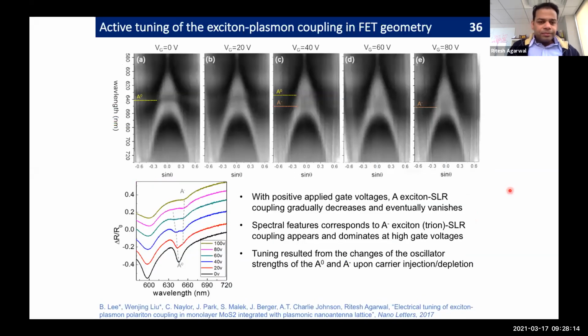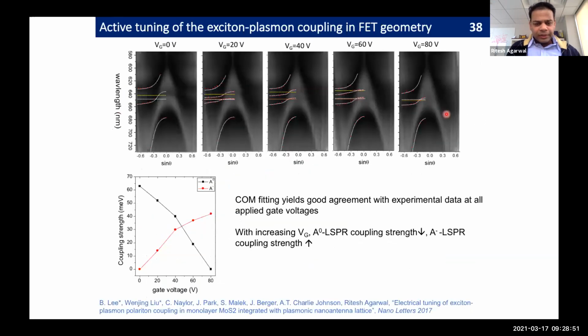So indeed, at 0 gate voltage, we saw this level repulsion at the A exciton region, and then as we injected carriers, we started to see a weakening of this A exciton level repulsion, and some perturbation in the line shapes at the trion, because we're injecting carriers, so it starts to form trions in the system. And as we inject more and more carriers at larger gate voltages, the A exciton level repulsion simply disappeared, and we started to see more perturbations in the line shape at the trion resonance. I'm not going into the details.